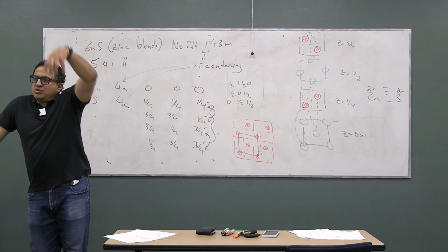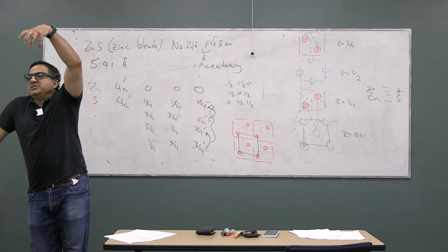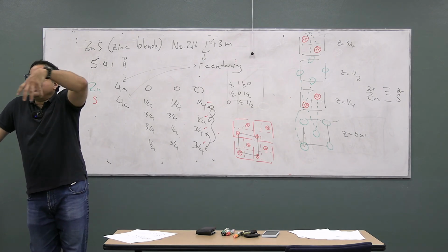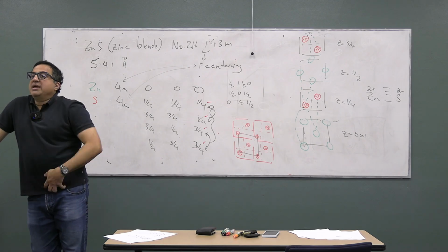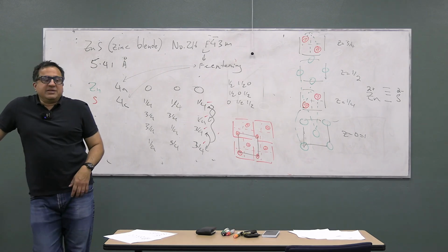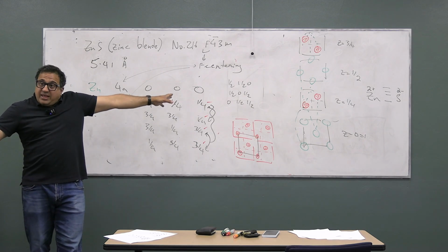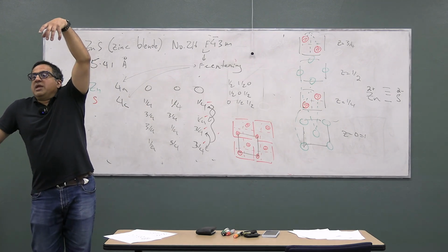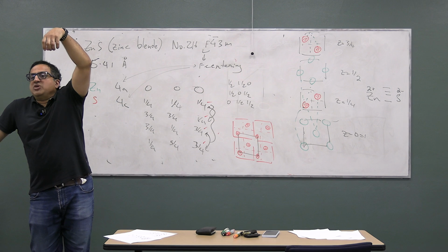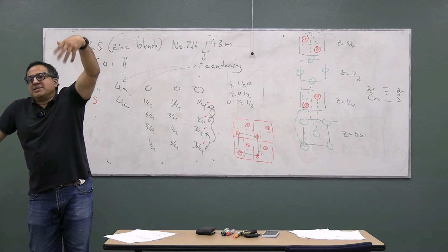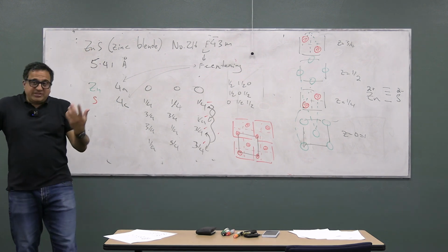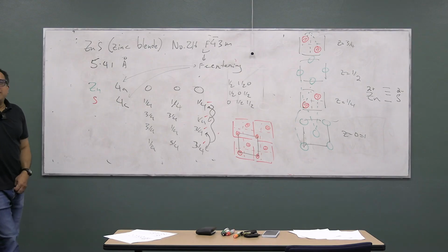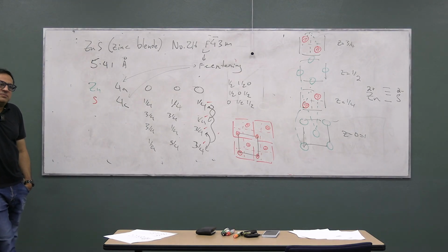So you go from the parent structure, which is diamond, to the zinc blende structure just by alternating the atoms. In terms of expressing the structure, you go from the Fd-3m space group, where you have only one atom that becomes another atom in the unit cell of the same kind, to F-43m, where the two sublattices are separated by 1/4, 1/4, 1/4. Is all this making sense?